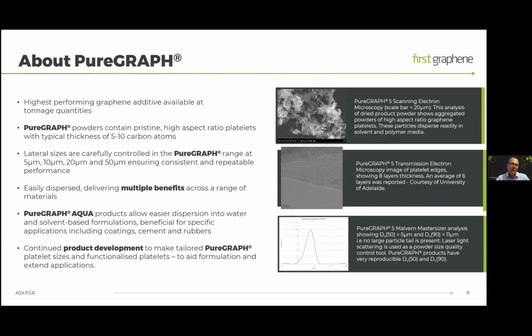There's some data shown on this slide. So the top image is scanning electron microscopy, which is 100% of the powder just simply placed into an SEM. And you can see these high aspect platelets distributed through this material. Further analysis by techniques such as Raman, AFM, and TEM shows that the platelets themselves are typically less than 10 carbon atoms.